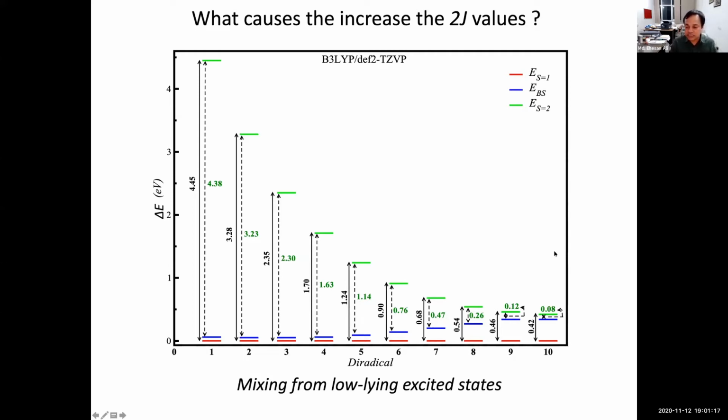But what we see exactly is that when we are increasing the number of benzene rings, the higher states are coming closer to the lower spin states. But for the ferromagnetic interaction, the spin is equal to 1, meaning those are aligned parallel, so those are always in the ground state. So there is no doubt that we are getting antiferromagnetic exchange interaction. Apart from the mixing with the higher spin state, we don't see any other issues in the calculation of the exchange interaction.